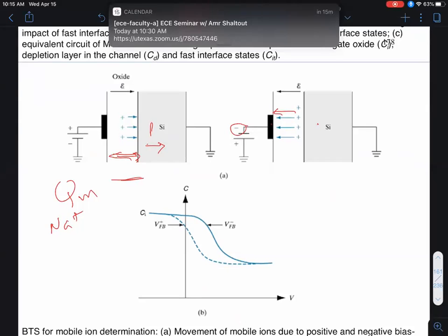So you make a MOS structure, you first apply a positive gate voltage, you measure the CV, and we know how to calculate the flat band voltage from that. But then you heat it up to allow these ions to drift more easily, apply a negative voltage, measure that. And the difference between the two, delta V flat band, will be the mobile charge divided by Ci. Okay, so you can measure the mobile charges, the source of which are sodium ions.